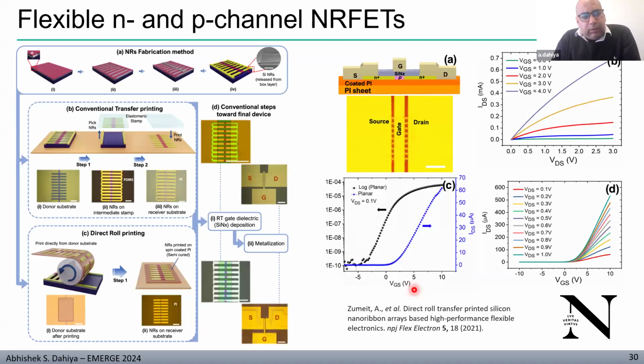This is the first example where we have used direct roll printing to fabricate field effect transistors of both N and P channel. So this is step one. Here we have fabricated the nanoribbons. We have used our roll printing approach to print them onto the flexible substrates. And then we have used a room temperature process to deposit the dielectric as well as the source, drain, and gate metal electrodes. The performance is shown on the right here.